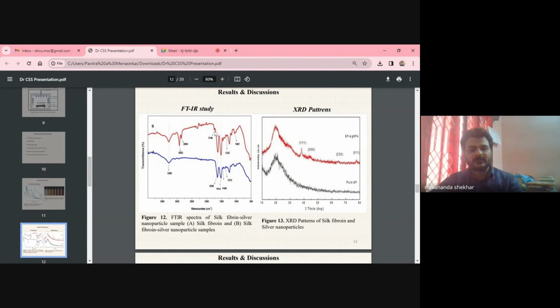This peak corresponds to the formation of silver nanoparticles, and it confirms the formation of silver nanoparticles, because in silk fibroin there is a tyrosine molecule that can help to reduce the silver ions into neutral silver atoms. So this is the confirmation by FTIR spectroscopy.